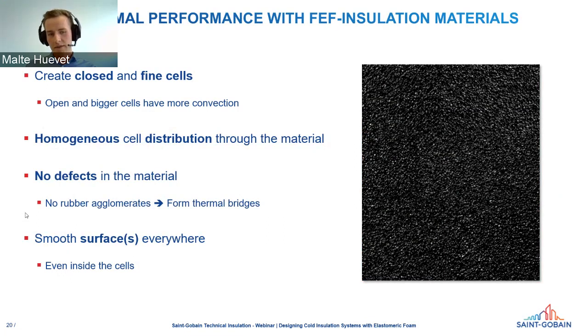That could happen sometimes, for example, if there are rubber agglomerates, which are also defects. That's mainly caused by unexposed propellant, for example. And these rubber agglomerates, mainly a rubber bulb, you can say, an unexposed part of rubber compound inside the foam. And of course, because it's a solid piece of rubber, they form thermal bridges. That's always what we want to avoid and what we don't want to have in a thermal or a technical insulation. And what we also need is a very smooth surface. And even inside the cells itself, the surface needs to be as smooth as possible.